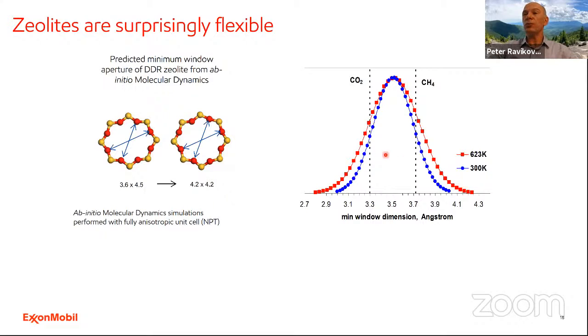And what is interesting, if you put a nominal size of a CO2 molecule and a nominal size of methane molecules, you can see that flexibility is important for this material. So there is no clear cut that, for example, methane is totally excluded from the structure and CO2 just diffuses easily without colliding with the window oxygen atoms. So this flexibility needs to be taken into account.